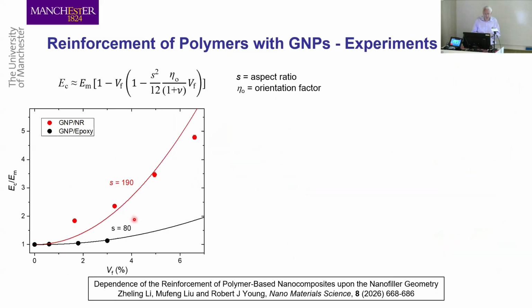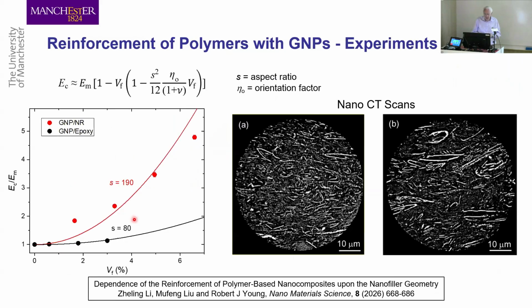And you can see aspect ratio is important here. This is an experiment we did where we plotted the modulus of the composite divided by the modulus of the matrix against the volume fraction for different aspect ratios. And you can see here the higher aspect ratio particles give better stiffening than the low aspect ratio particles. And you can measure the aspect ratio from the CT scans.